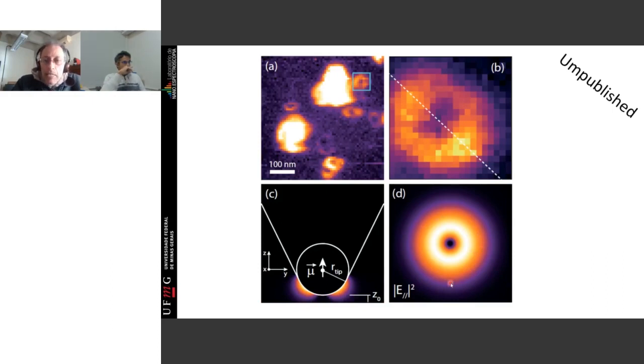And what happens is that graphene does not respond to light polarized perpendicular to the graphene plane. It only responds to light polarized along the plane, which is perpendicular to the antenna itself. Then the illumination has this shape, and this is what you're seeing here. The particle that was being imaged was much smaller than the illumination area itself. So what you did with the graphene nanoparticle was you made a picture of your illumination area.